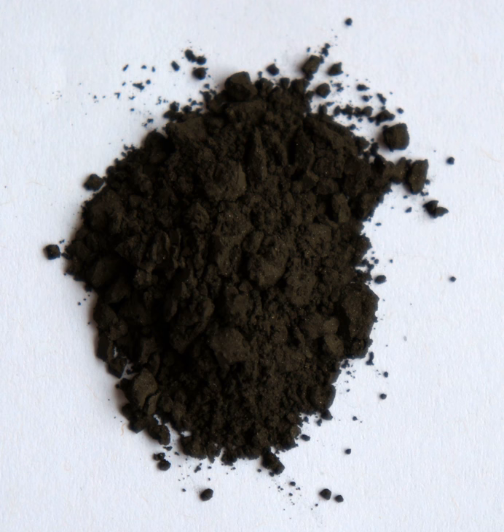In the laboratory, titanium hydride is produced by heating titanium powder under flowing hydrogen at 700 degrees Celsius, the idealized equation being Ti + H2 → TiH2. Other methods of producing titanium hydride include electrochemical and ball milling methods.